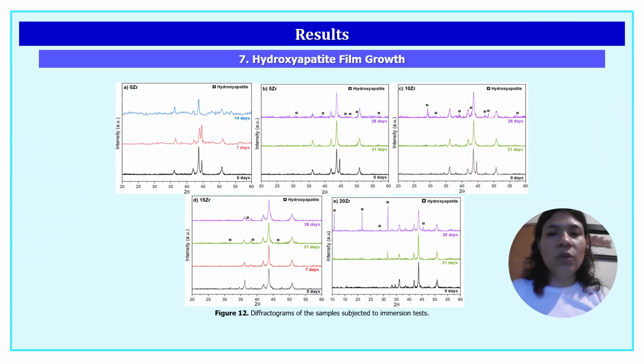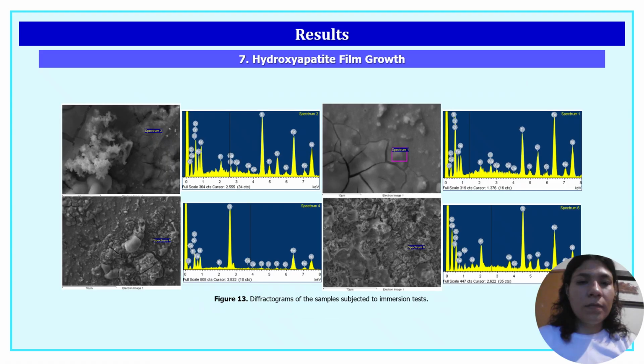Finally, the immersion test conducted in SBF for 7, 14, 21, and 28 days allowed the observation of hydroxyapatite layer formation. In figure 12, the different samples are shown after the various immersion periods, indicating that the samples with zirconium content exhibit hydroxyapatite after 28 days of immersion, with the 20 zirconium sample showing the highest peak intensity, which is linked to the crystallinity of the layer. Figure 13 presents EDS micrographs showing the chemical composition of the layer.